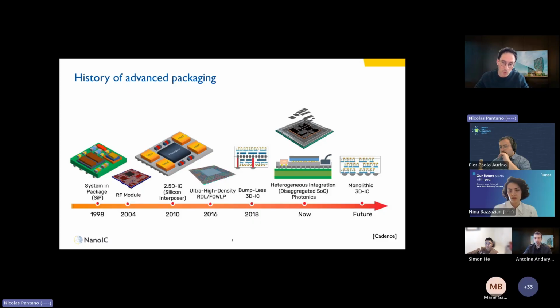And then the next step was kind of logical. If you start to use all the tricks to use the 2D plane, at some point you have to do 3D. And 3D has started to happen with images, where we have the pixels combined with the memory and the DSP, and in a bumpless fashion, so what we maybe call today hybrid bonding. Images was probably the first product that has adopted that hybrid bonding technology. And this is something we actually continue to see.